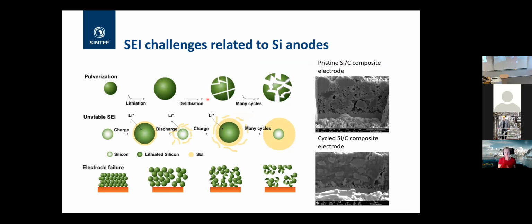For silicon, and this is something that I wanted to mention, because some of you might have heard about silicon used as anodes in lithium-ion batteries. Tesla has already started to implement silicon in their graphite anodes. There are also several companies in Norway that are working on producing silicon materials for lithium-ion batteries. Silicon has a really big theoretical capacity, about 10 times that of graphite. But if you are going to utilize the capacity of silicon, you see that it expands about 300 to 400% compared to its original size.